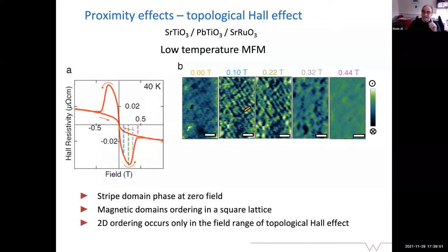I have to mention that we didn't measure the topological Hall effect in the same run. We measured it in a separate run, but it's on the same sample, so it's not something different. And then you see that already at 0 Tesla, we see some patterning, which is interesting because it doesn't fit with the step terraces. So it's not the same. And then with the magnetic field, you see that it evolves into a square lattice.